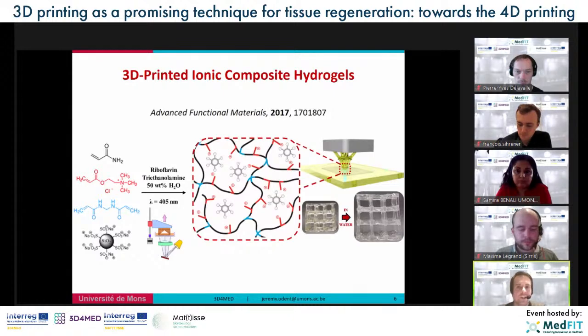So let me move to some examples of what we actually develop at the university. Here we recently demonstrated a family of ionic composite hydrogels with excellent mechanical properties that can be rapidly 3D printed at high resolution using commercial stereolithography technologies. The key of our formulation is the addition of sulfonate-modified silica nanoparticles to an ammonium-containing polyacrylamide hydrogel.